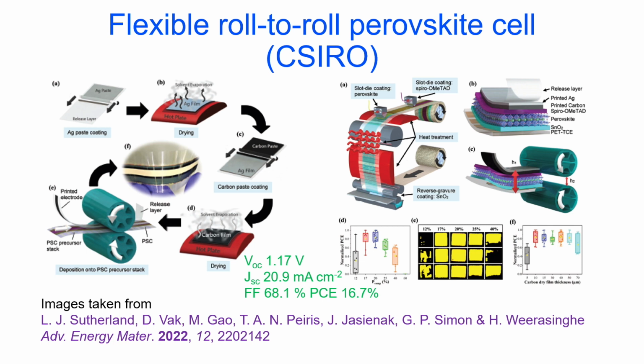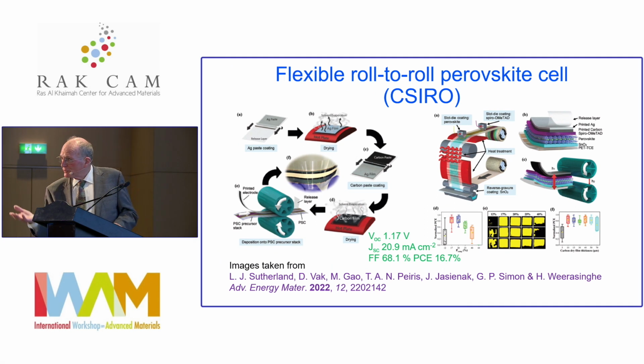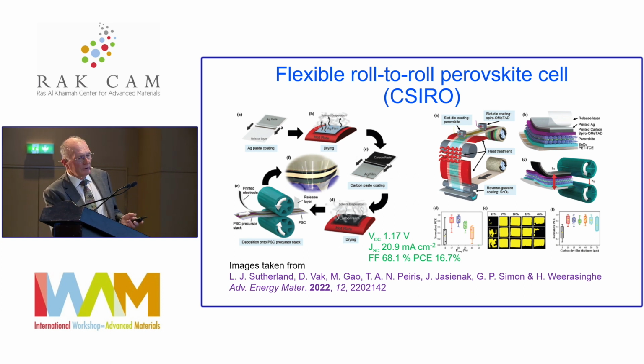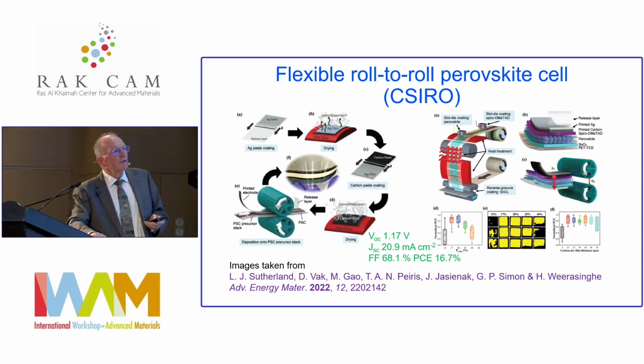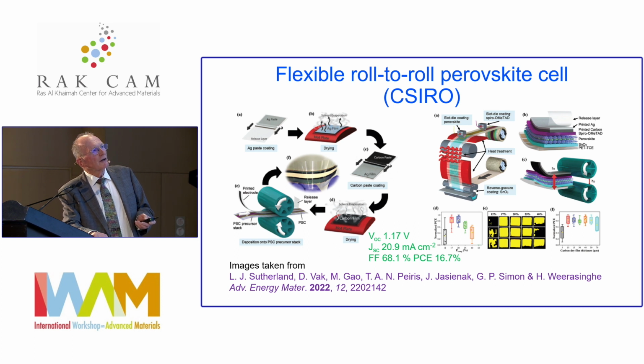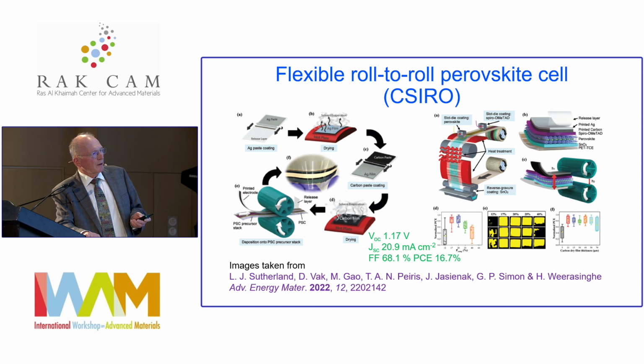So first the silver is deposited, then dried by solvent evaporation, then a carbon paste is deposited on that and dried by evaporation, and then it's transferred to the partially assembled solar cell by this deposition technique, which is a reverse gravure technique in which rollers are turning clockwise and counterclockwise against each other, and the printed electrode that I've described there is released onto the surface of the partially assembled solar cell under the pressure of the roll-to-roll calendar press printing process. Now, the rest of the solar cell is again reverse gravure deposition of tin oxide, slot die coating of the perovskite, and then slot die coating of the spirocyclic hole transport material. And there is a mild thermal process involved in that.